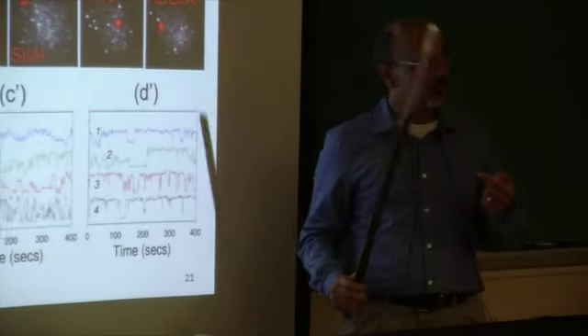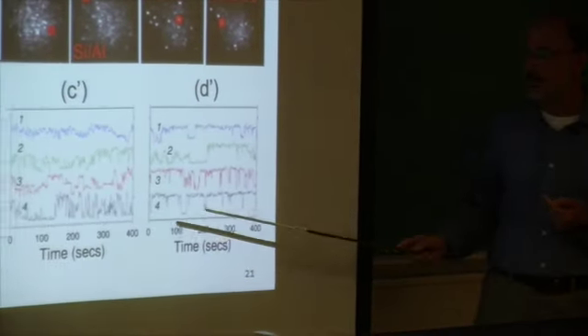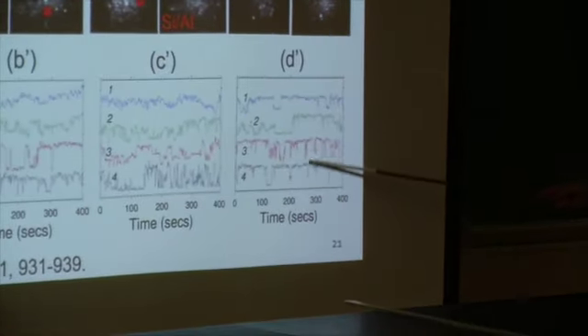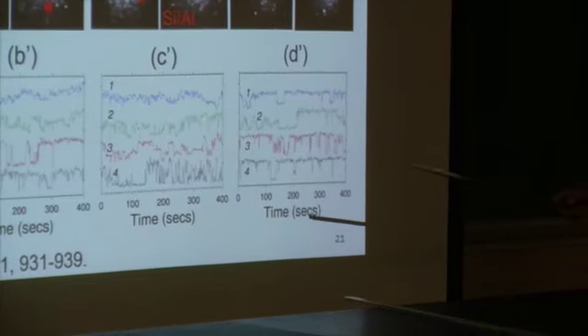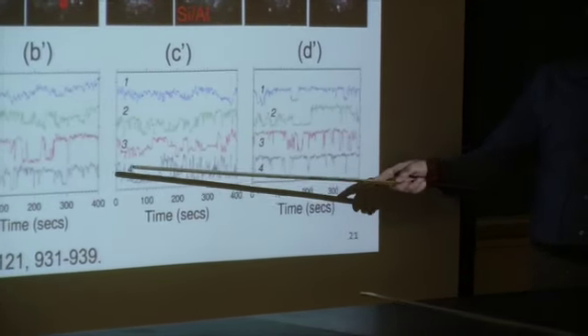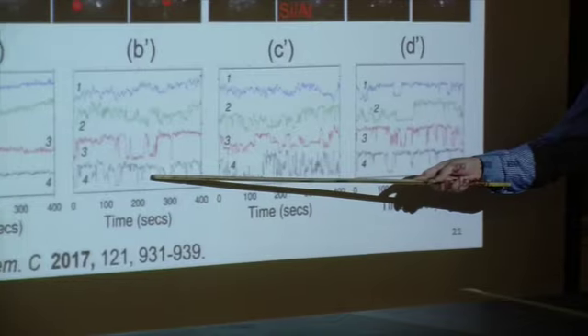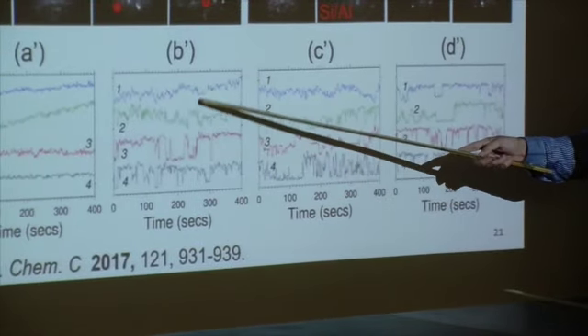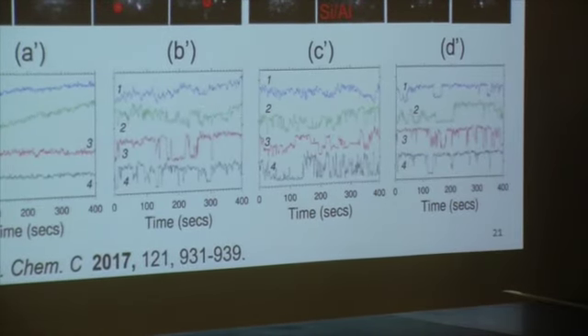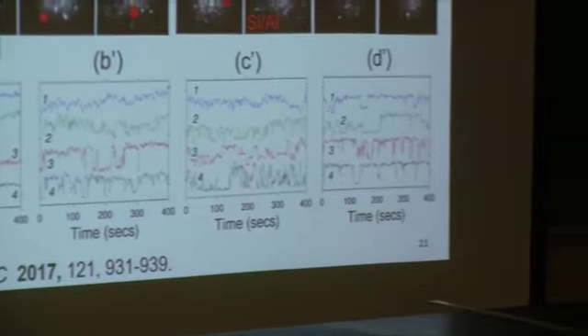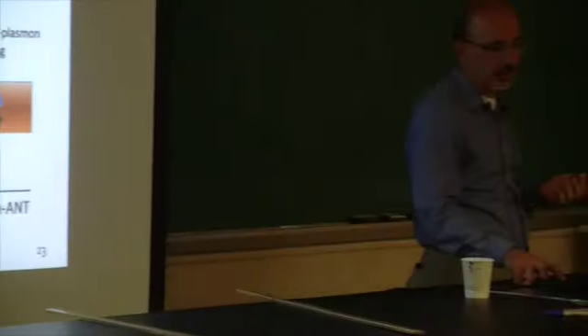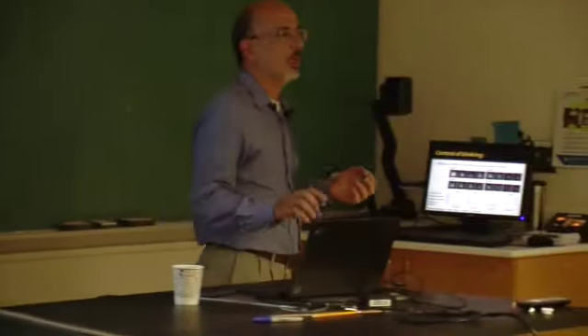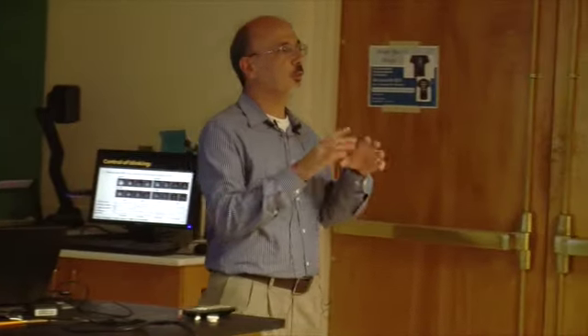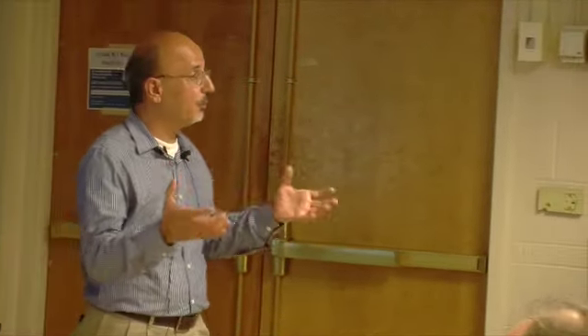The concentration that's supposed to give us blinking is this one, which all of them show the blinking. And then by introduction of aluminum oxide, you can change the pattern of the blinking. And the reason behind that goes to the fact that silicon is full of defect. Amorphous silicon that we use is full of defect.